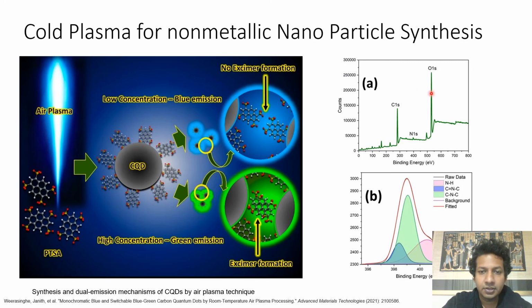The XPS survey spectrum shows two prominent peaks of C1s and O1s. The N1s peak at 401 electron volt indicates that air plasma can dope nitrogen into the surface of carbon quantum dots in absence of any chemical nitrogen source. The atomic concentration of nitrogen is 1.55%.